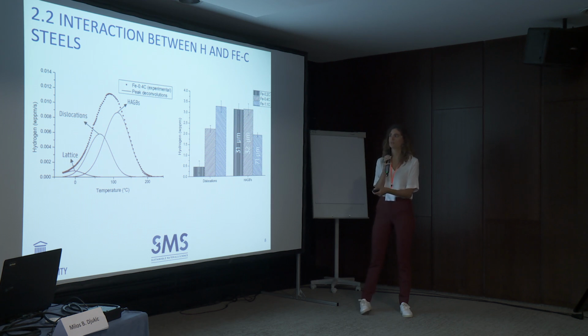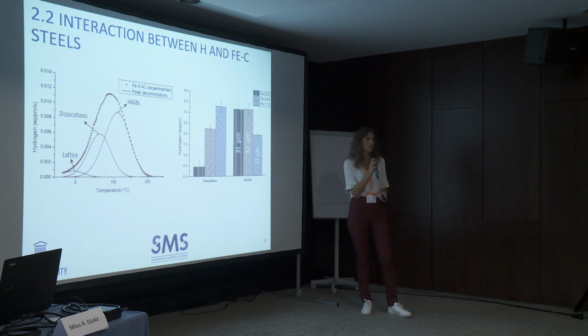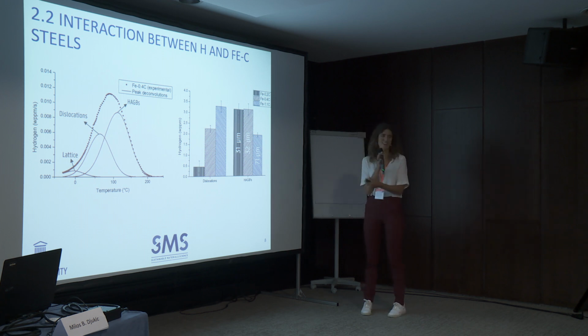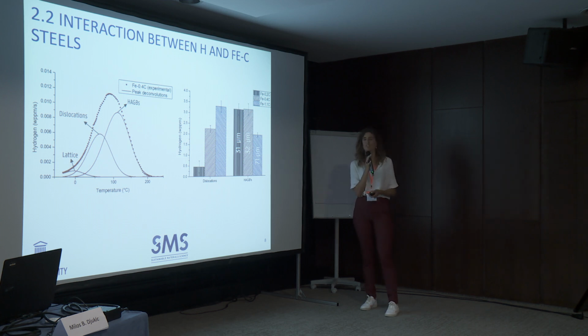There's also a small amount of hydrogen trapped at lattice positions, but this can be ignored for the rest of this presentation because the value is very low. Here is some sort of summary of where hydrogen is trapped and how much hydrogen is trapped at the trapping sites.